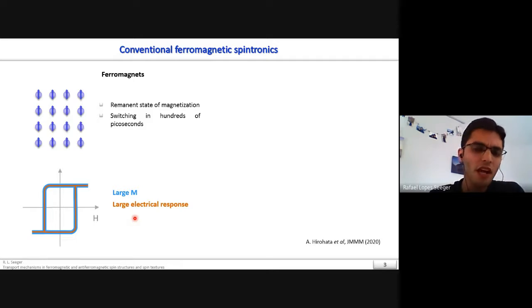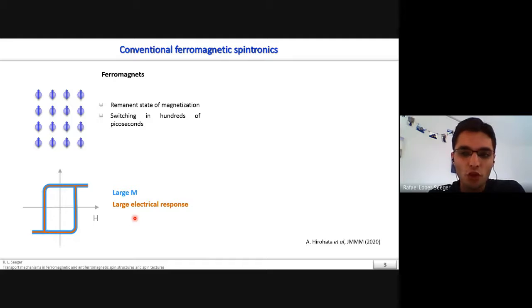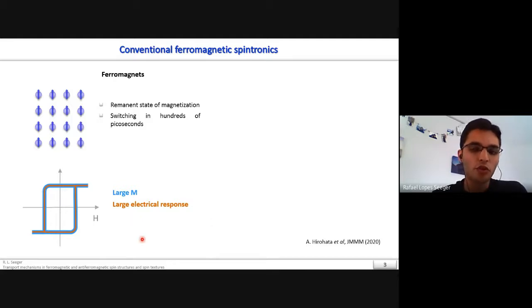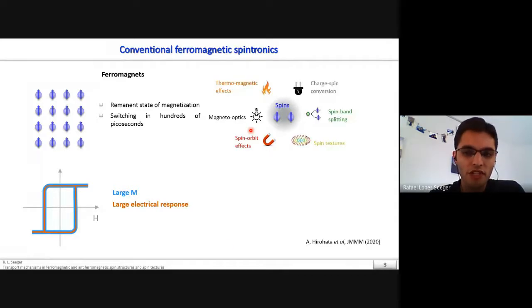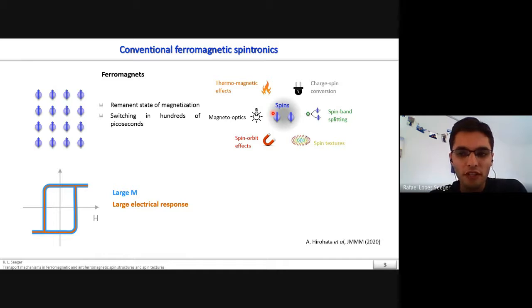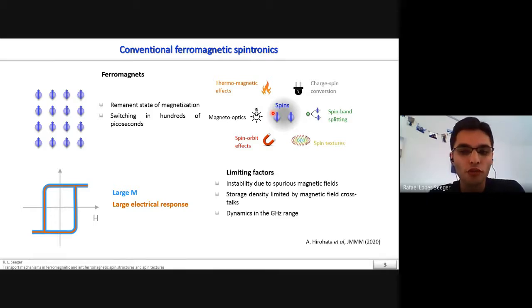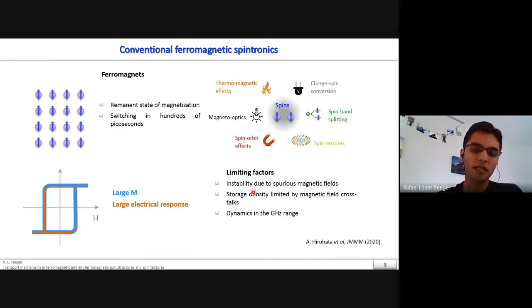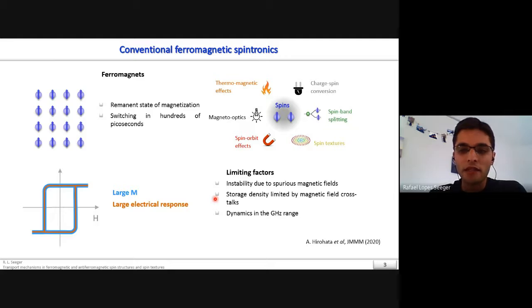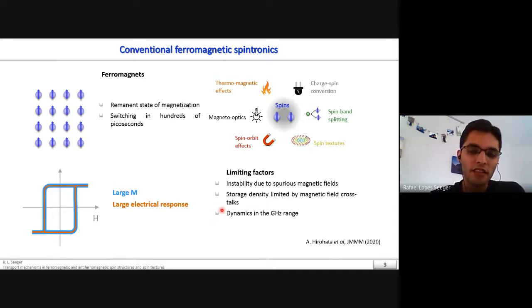Concerning magnetoresistive effects, ferromagnets may display a large electrical response associated with the magnetization, and very often in spintronics the discovery of new magnetoresistive effects led to applications. Beyond magnetoresistive effects, the interaction of physical entities such as light, heat, and electricity with spins in ferromagnets has attracted a lot of interest. However, ferromagnet-based devices also offer some limiting factors, such as instability due to spurious magnetic fields, limits to high storage density due to magnetic field crosstalk between devices, and dynamics in the gigahertz range that limits the maximum switching velocity.